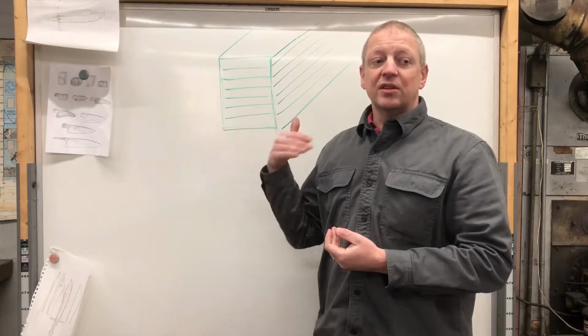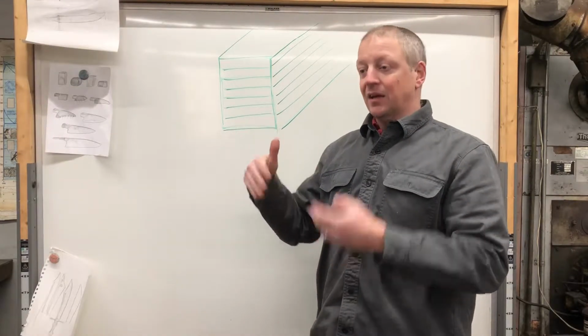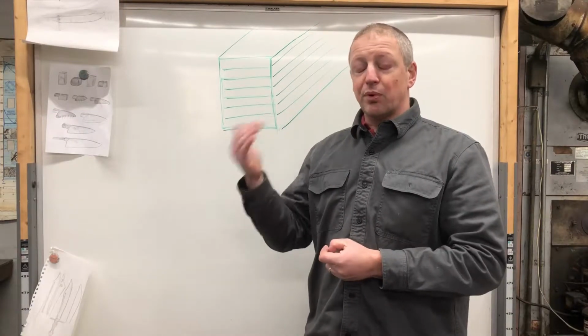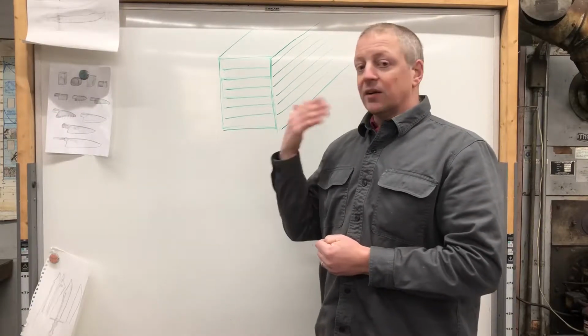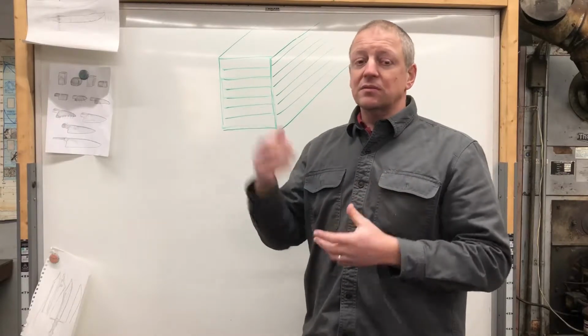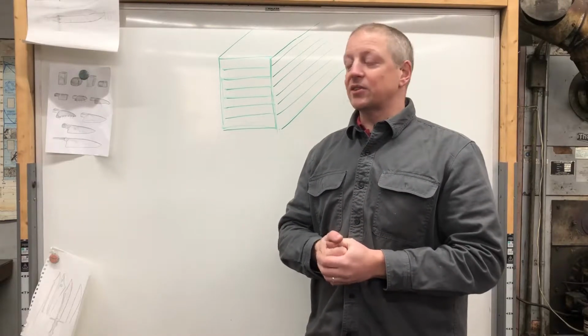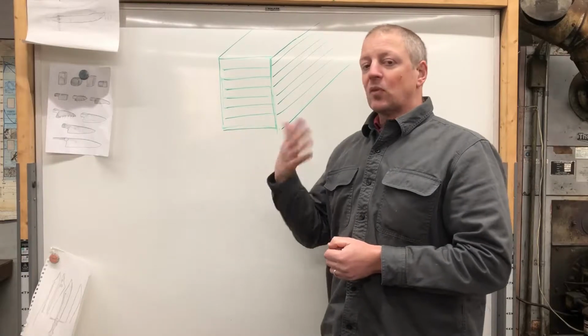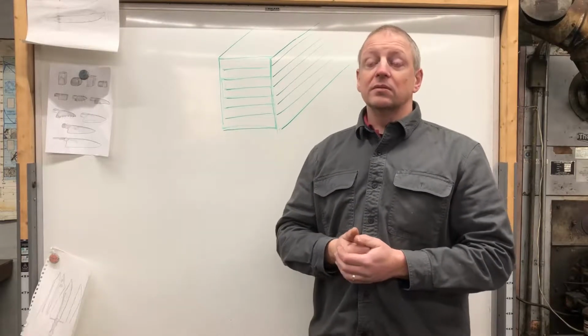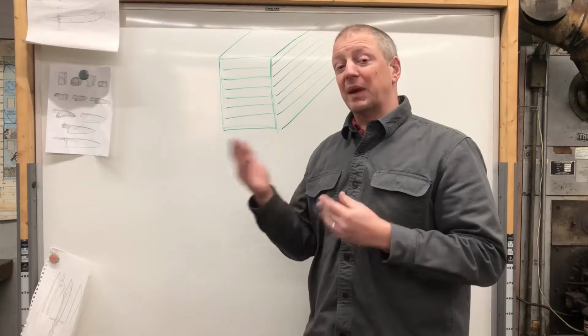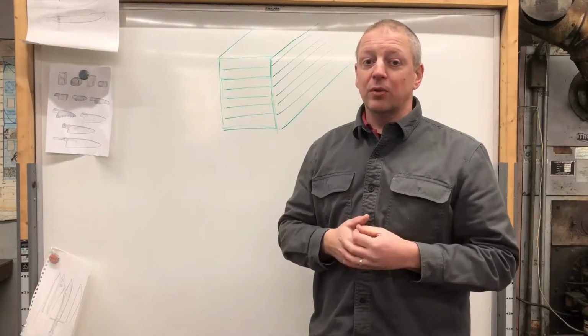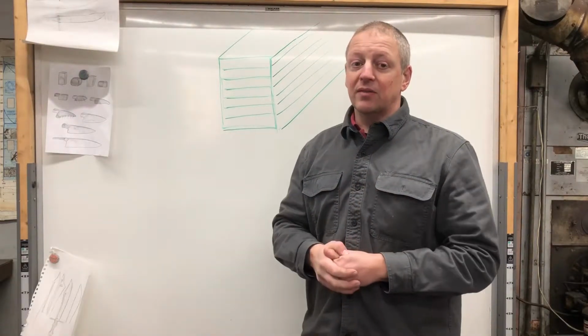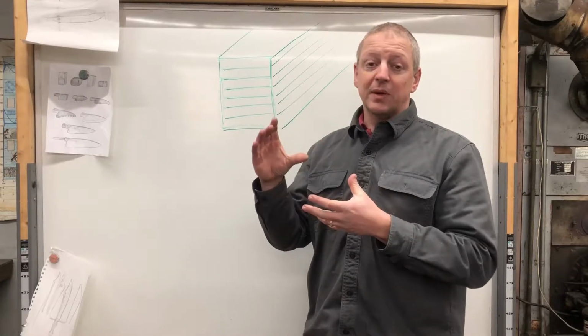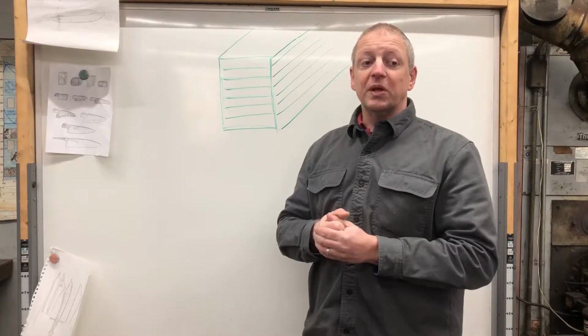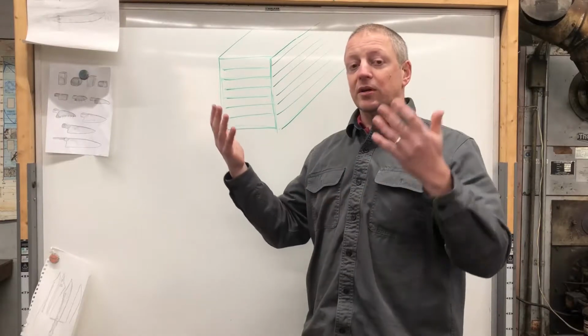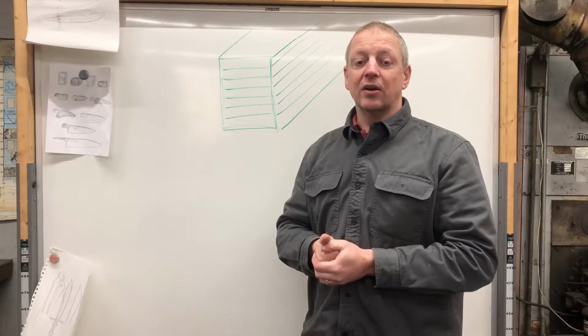At this stage, once the billet is at welding heat, that nice bright yellow, verging, not white, but getting towards that direction, we let it soak in the forge. Depending on who you talk to, depending on how clean your layers were, 5 to 10 minutes. It also depends a lot on the size of the billet. For a larger billet, you'll want to let it sit a bit longer to make sure that temperature has really gotten all the way through.